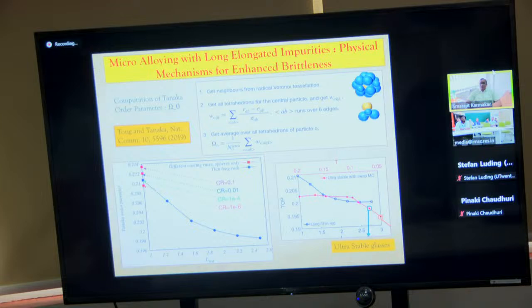Although we could not stop shear bands, so sometimes the shear bands are promoted, but the yielding process is delayed. So the good advantage is that the modulus goes up if you increase the amount of long rods, and your yield will happen at a larger strain. But when it happens, it will happen in a catastrophic manner. So the shear band is something which we could not stop or diffuse. Though it has some pinning-like effect, it's not similar to what pinning does.